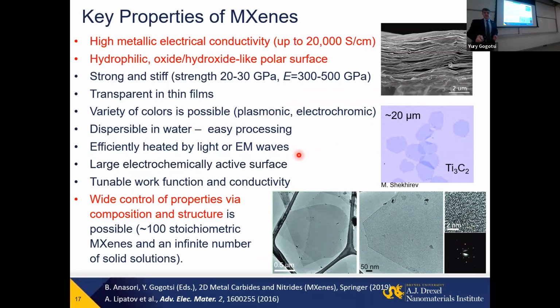Plasmonic colors, very efficient light to heat conversion, electrochemically active surfaces, chemically and electrochemically tunable work function, and other properties. But the key thing with these materials, as I mentioned in the beginning, is that you can tune their properties. You can shift the Fermi level. You can do reversible redox reactions on the surfaces here. Because nanotechnology, nanomaterials, is not about making things small. It's about controlling at the nanoscale. And this is exactly what these materials allow us to do.